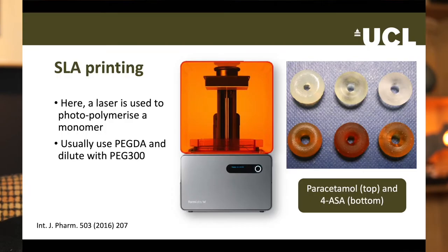In the first method, which is known as stereolithographic or SLA printing, objects are made from a resin and a laser is used to photo-cure molecules together. The resin contains small molecules known as monomers. The resins we use are usually based on polyethylene glycol diacrylate. The diacrylate groups can react and bind together when excited by laser energy, although we usually add a photo-initiator to help speed up the process.